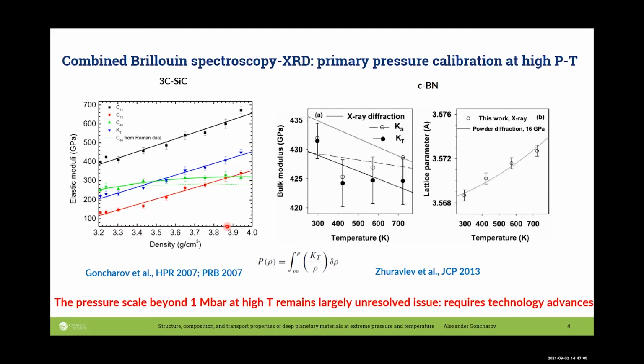So what we did more than 10 years ago, we looked at the cubic covalent materials like silicon carbide, cubic boron nitride, and used them as primary calibrants to try to determine the high pressure scale. We also tried to determine a high pressure scale at high temperature. Unfortunately, at that moment, the technique was not developed sufficiently, so we couldn't get beyond a certain temperature range, say 750 K, and certain pressures like 75 GPa. So our results are, in a sense, very trivial.